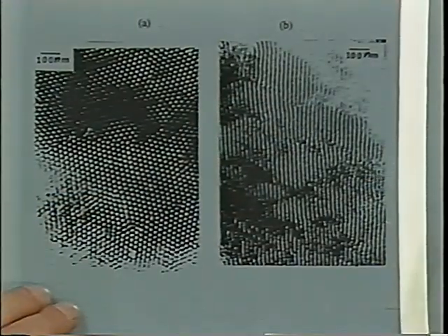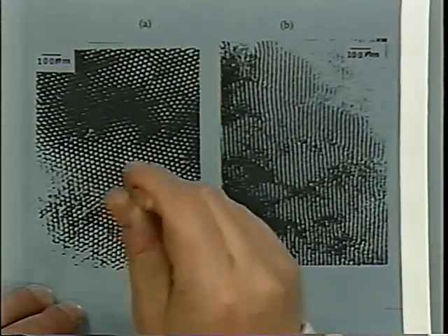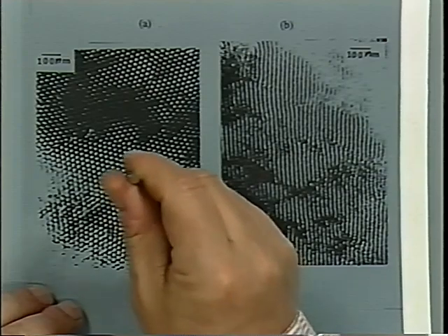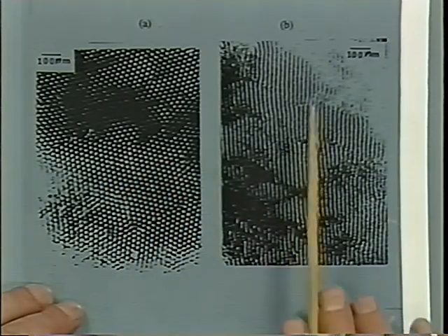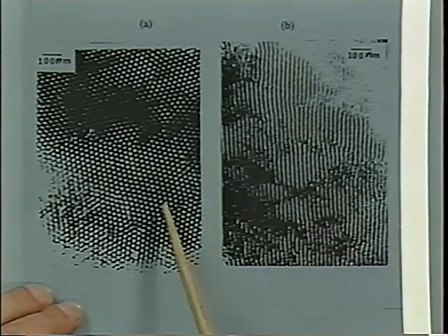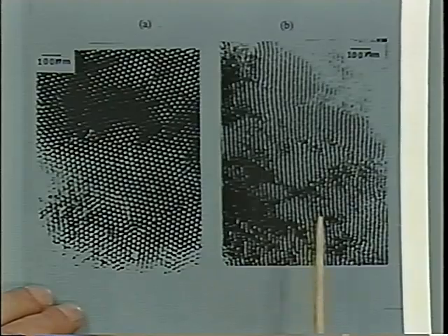A larger picture of the structure is given here. The cylinders are fairly uniform, the director is fairly uniform. You can see that also sideways. The hexagon is also fairly uniform in its alignment, but there are still some grain boundaries, some defects which couldn't be avoided.